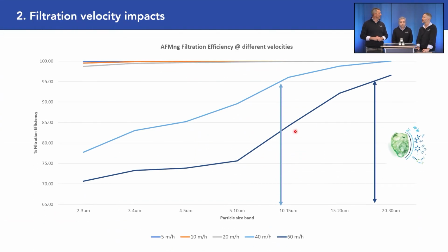Impact number 2, filtration velocities. If we look at how fast your water is being pushed through your bed, so again, it's cubic meters per hour per square meter, we did testing of different flow rates. If you look at the bottom, again, it's the particle size band, between 2 microns and 30 microns in this case, and percentage removal of 65% up to 100%.